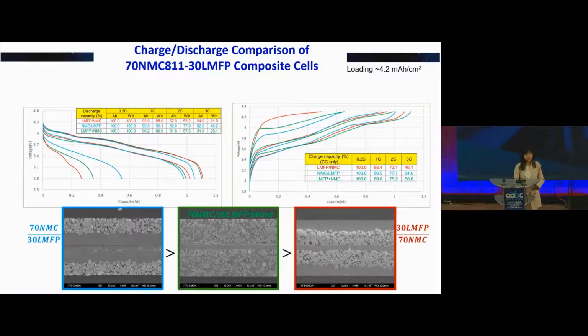In line with the aforementioned LMFP-rich composite cell, we also noticed a similar trend in the so-called NMC-rich composite cell. This one had 70% NMC with 30% LMFP. Among these cells, you can see that the dual layer cell with LMFP in the bottom layer had the best charge and discharge power capability, surpassing the so-called composite cell and the cell with the LMFP in the top layer.